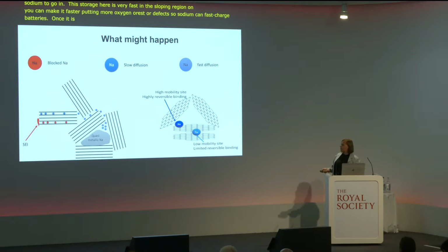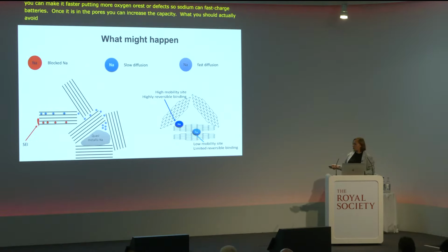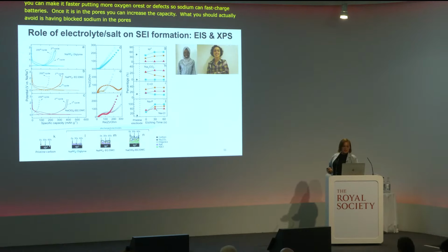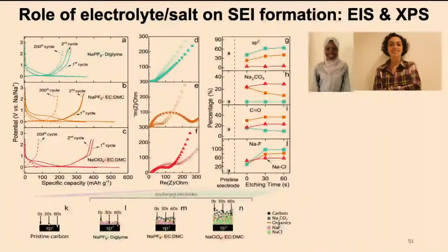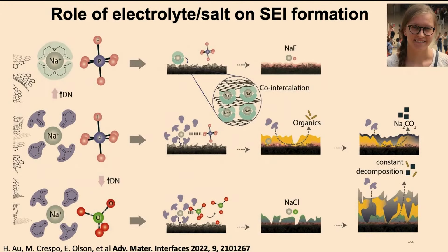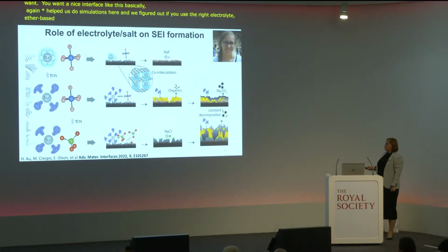What you should avoid is having blocked sodium in the pores or too small interlayer spacing, and the SEI formation. I'll skip this, but I told you that in batteries it's not only important to work on materials, it's also important to understand the interface. Just by changing the sodium salt and the solvents in the electrolyte, you get a completely different interface. This is not the interface you want. You want a nice interface like this. Again, Emilia helped us do some simulations here, and we figured out that if you use the right electrolyte, an ether-based electrolyte, you get a very nice interface. If you use sodium perchlorate with a carbonate electrolyte, you get a terrible interface.